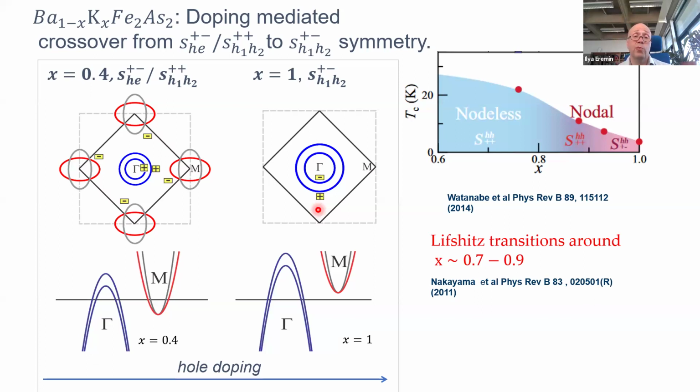And that is more or less given in helium-3, but in solids there is always a problem, because we know that there are crystals and the symmetry is lower than the fluid, and therefore in crystals there is always some preferred direction for the scattering, typically along the bonds, and that usually always likes to have even parity superconductivity. So I would say you need to go to a system with spin orbit coupling, in my opinion.